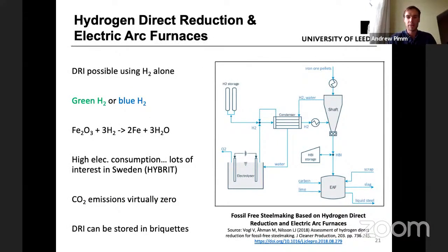As I mentioned already, DRI typically uses natural gas, methane, split into carbon monoxide and hydrogen, and you use that mixture of reducing gases as reductants to extract the oxygen from iron ore, giving you the pure form of iron. It's possible to do this using hydrogen alone. You can use different mixtures of hydrogen and carbon monoxide, and it's possible to do it using hydrogen alone, and it's been done in a pilot plant. There was, I think, a plant in Trinidad, in the Caribbean, in the 90s that tried to go this way, but the economics at the time didn't stack up, and they had various issues, which I don't think were really related to the fact they were using hydrogen.